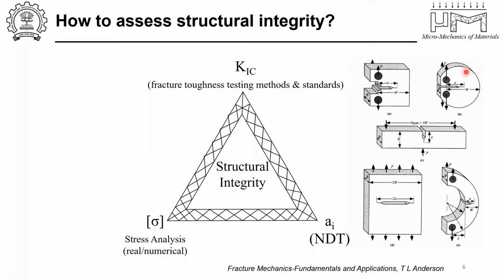For example, if you have a disc-shaped specimen, then you have a disc-shaped tension specimen, if you have a half disc-shaped specimen, then you have something like this. When you have brittle materials, then you have what is called a single-edge notch bending specimen, and so on. So there are tons of geometries that have come from practical consideration. So I'm going to tell you why we came up with yet another new geometry, and that origin has come from us trying to measure fracture properties of materials at smaller dimensions or smaller length scales, where none of these geometries or their boundary conditions would work very well.